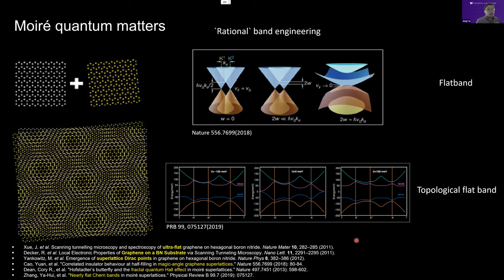Is you take two sheets of two-dimensional material and rotate them with respect to each other by a very marginal twist angle and form an interface together. Now, what you can see is that the original lattice forms a reconstructed, very large scale lattice, okay? Originally, for example, for graphene it is 2.5 angstrom scale, but now it forms a nanometer scale moiré superlattice. And this superlattice gives us very interesting phenomena, such as we can use this twist angle and also gates to rationally engineer our band structure.